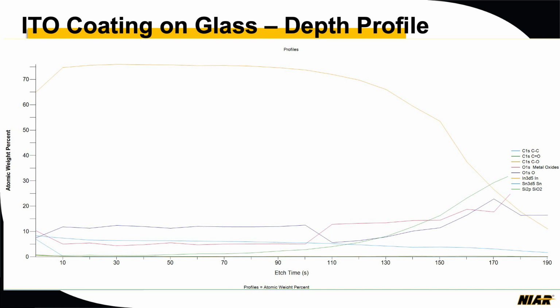Now, we don't have a baseline material where we can do a depth profile and do a standard. So that's why this one is an etch in seconds. That's how we basically set the parameters: for how many seconds it is etched, and we do a test every 30 seconds or 60 seconds, whatever parameters we select. And we collect the data and basically go on again for the etch process.